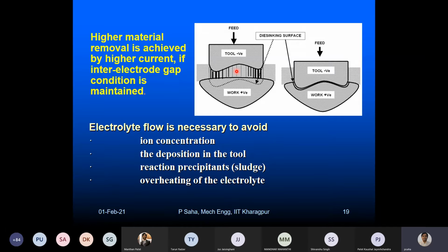This is one thing. Second, the electrolyte may be heated very high. When will that happen? If the electrolyte is flowing but the flow rate is not sufficient, the heat produced is so much that the electrolyte may start boiling. That is another difficulty other than gas bubbles. We have to avoid it, because it will hinder the electrochemical process. So to avoid overheating, we have to ensure the electrolyte flows at sufficient velocity so that boiling of the electrolyte cannot happen. Also, because of the electrolyte flow across this gap, there may be some difference in electrolyte temperature, which will also give a different electrochemical machining rate.